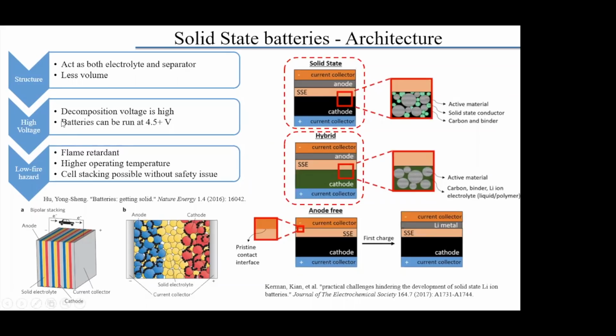At the same time, the liquid electrolytes can decompose if you run them at more than 4.5 volts. And that's why a typical 18650 is limited to 4.2 volts. Some of them can go up to 4.4, but if you go beyond 4.5, they decompose and lead to a fire hazard. And these organic electrolytes are flammable. So that's another problem. And then some of these solid electrolytes have very, very high resistance to fire, and they don't catch fire easily, and they can operate at higher temperatures.